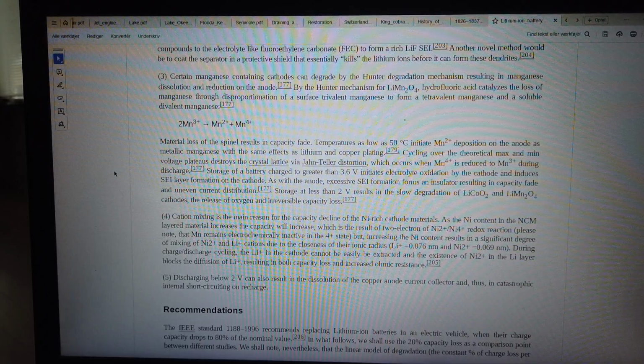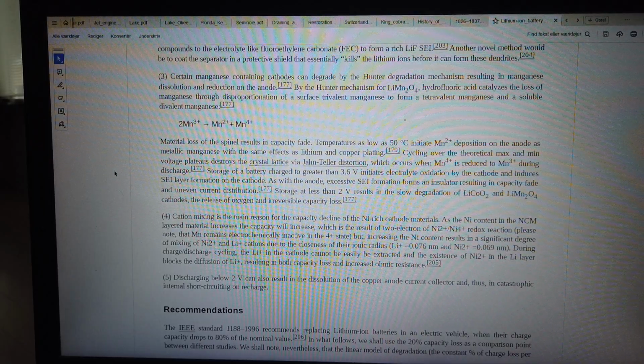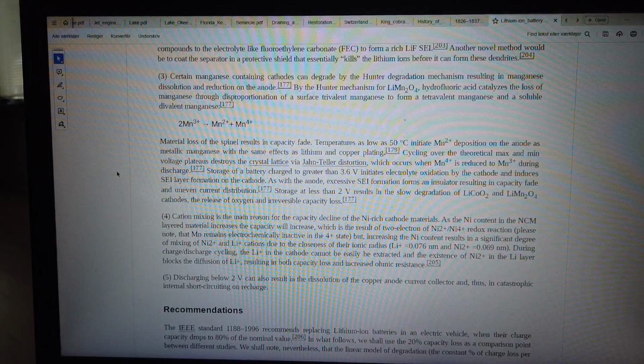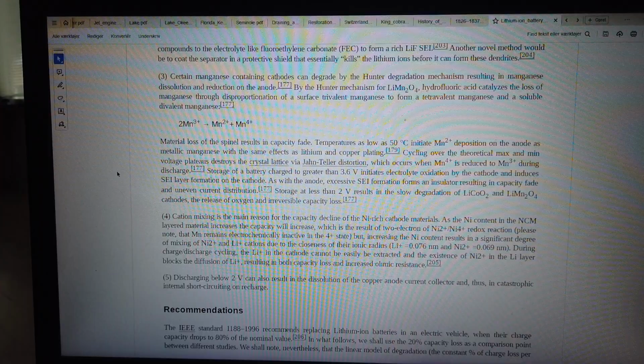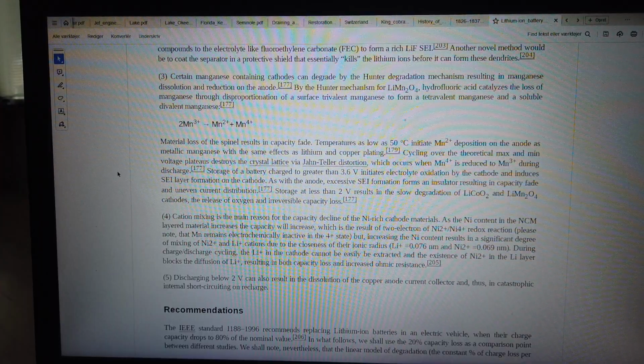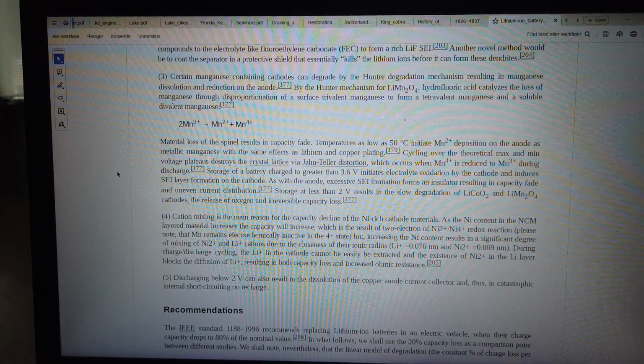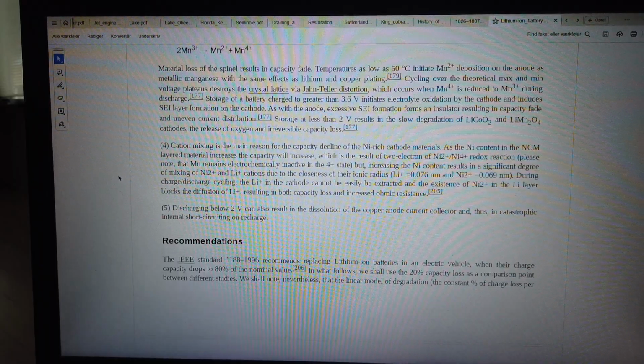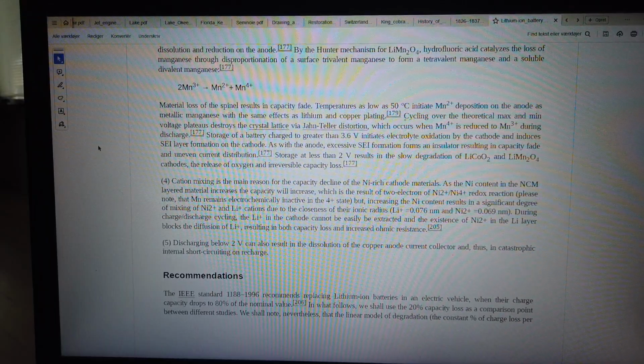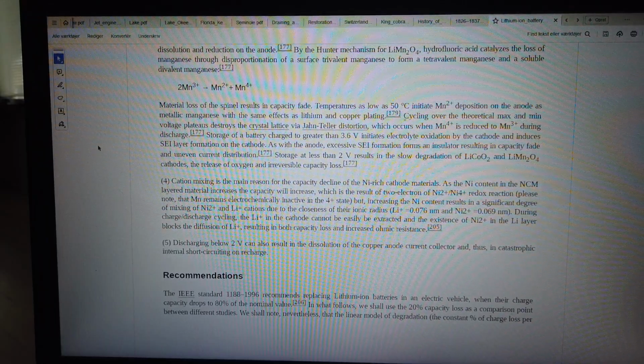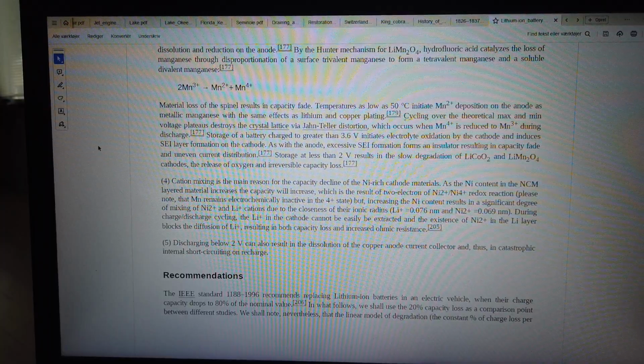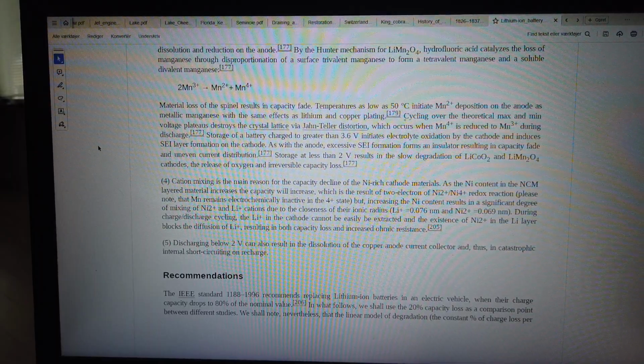Temperatures as low as 50 degrees Celsius initiate Mn2+ deposition on the anode as metallic manganese with the same effects as lithium and copper plating. Cycling over the theoretical max and min voltage plateaus destroys the crystal lattice via Jahn-Teller distortion, which occurs when Mn4+ is reduced to Mn3+ during discharge. Storage of a battery charged to greater than 3.6 V initiates electrolyte oxidation by the cathode and induces SEI layer formation on the cathode.